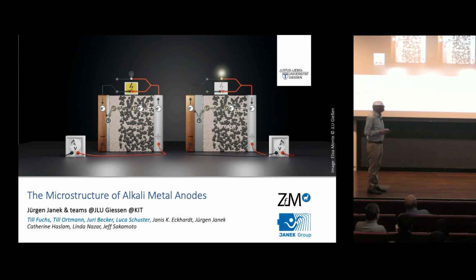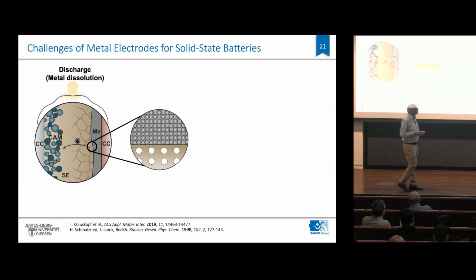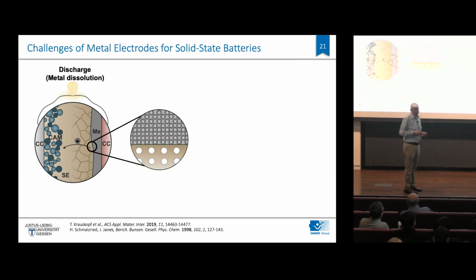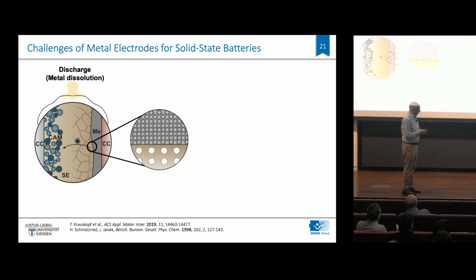So we started that a while ago, and let me introduce that by saying, okay, what is really the task? Now, if we go for a metal anode in an anode-free cell, and now here is the metal electrode, here's the cathode active material, here's the separator, here's the metal as a cartoon, and if we then in principle discharge the cell, the metal has to be dissolved, and that means an atom has to be dissolved into the electrolyte, and you create a little vacancy in the metal. You really get a vacancy in the metal, and that happens.